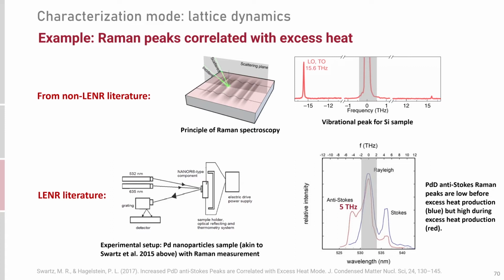To measure lattice dynamics, Raman spectroscopy is employed, where a laser beam is reflected off a surface of a lattice, and the photons lose or gain some energy from the lattice depending on the vibration. So this example here shows a peak that indicates lattice vibrations at about 15.6 terahertz frequency in a silicon sample. This is not a LENR paper. This is merely for illustration of the Raman spectroscopy technique. But then down here, we see a Raman spectroscopy technique employed in this LENR experiment with reports of Raman peak going up during excess heat production, suggesting strong ordered vibrations of the lattice.